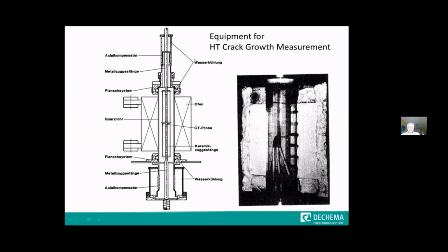And of course, the whole thing must be closed against environment, because in some cases we took very aggressive environments in here and let them react with our specimen. So you see there's a quartz tube around here. This is the specimen. What you can also see here is the wires for the measurement. So we did measurements by the so-called potential drop technique, which allows us to monitor the growth of the crack, the creep crack in the CT specimen, as it is shown here.